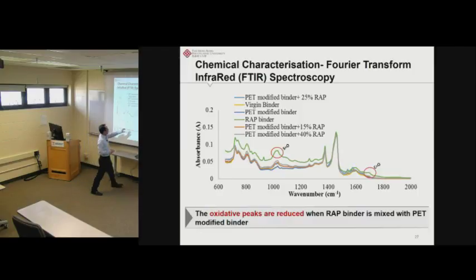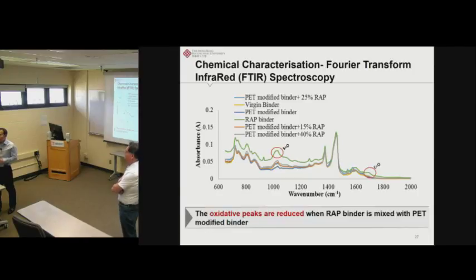But still, if we compare these curves, we can still see the change of these peaks. So these three, they are with the RAP binder. This one is without any. This one is the PET modifier. So we can still compare them, but I think you're right. We can just directly add the PET additive into the RAP binder without any virgin ones. But I think here we can already see the effect. If we directly add the additive into the RAP binder, I think it's more obvious.